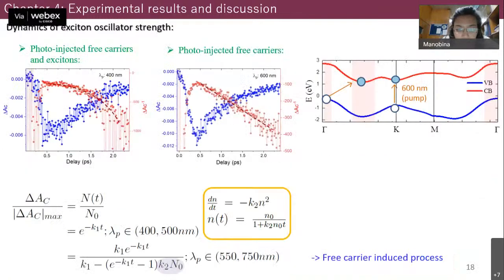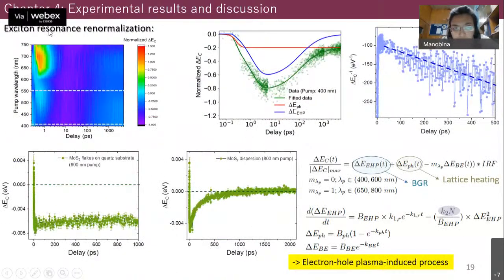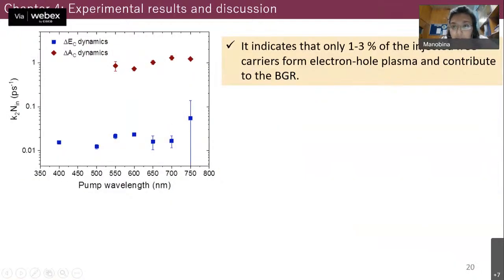We compare this number of carriers that participate in the oscillator strength dynamics, and from this resonance energy renormalization, we compare this number of carriers that participate in this screening, electron hole plasma formation. So with that, we find that only 1 to 3% of the injected carriers form the plasma and contribute to the band gap renormalization.